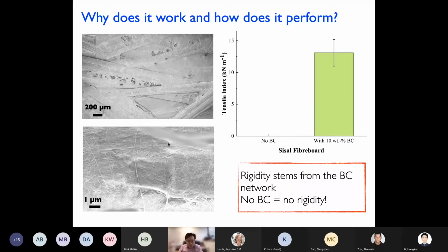And that's a close-up of the surface of one of these natural fibers, where you can actually see the bacterial cellulose nanofibers on the surface, well hornified, well bound together. We measure the tensile index. Again, tensile index is a paper industry test standard. Essentially, it's the force per unit width of a sample, mainly because the area is not well defined. So using megapascal is actually not a very relevant unit for describing tensile properties of these sort of rather porous materials.